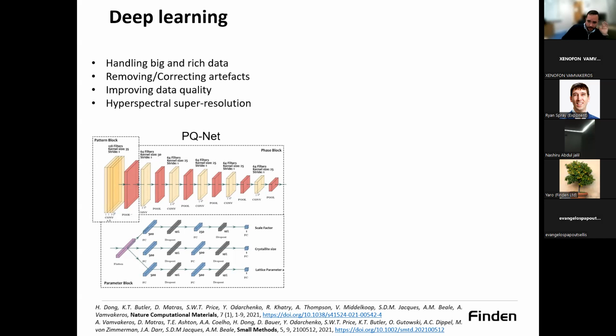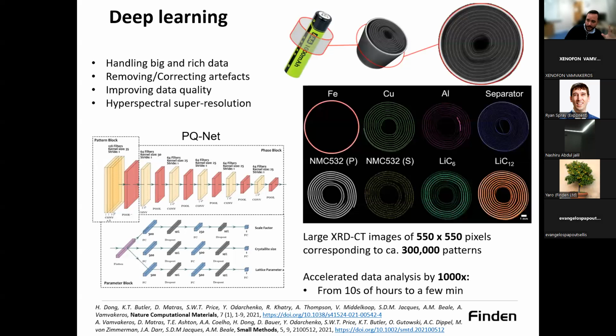And then we said, go now and analyze all these local patterns present in the XRD-CT dataset. Instead of taking 10 to 20 hours with conventional approaches to analyze, for example, a 2D XRD-CT dataset of this lithium-ion battery, the same results were achieved within a couple of minutes. So the development of this technology was game-changing for us.